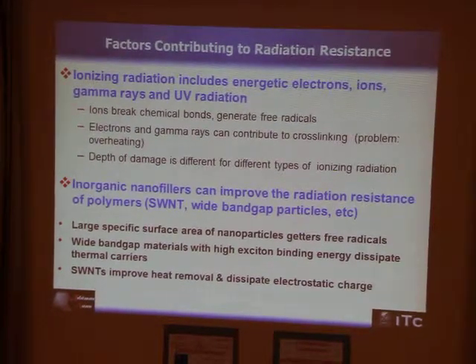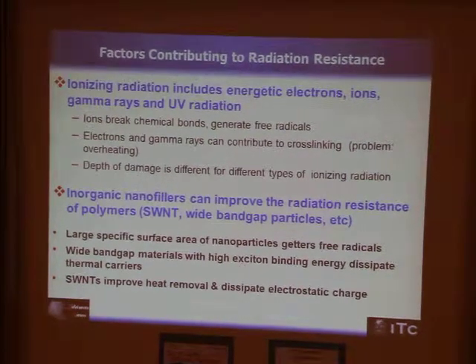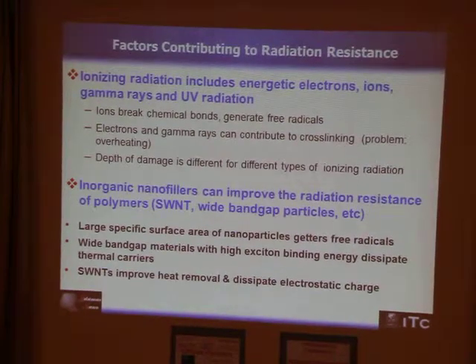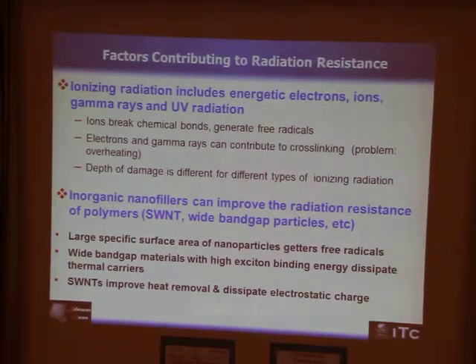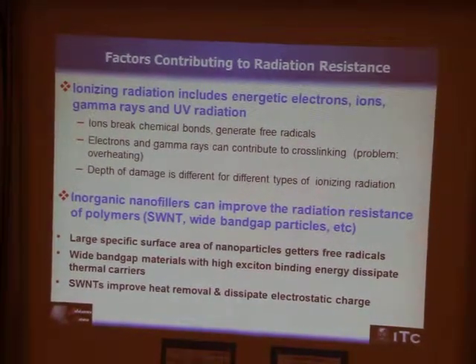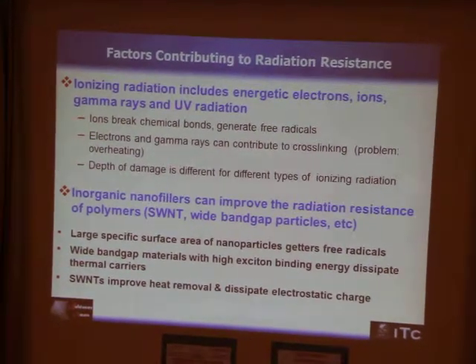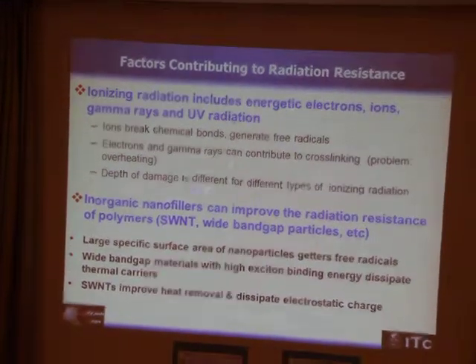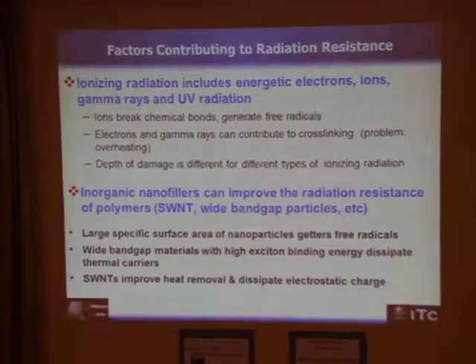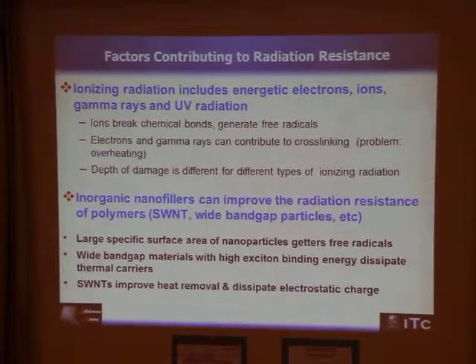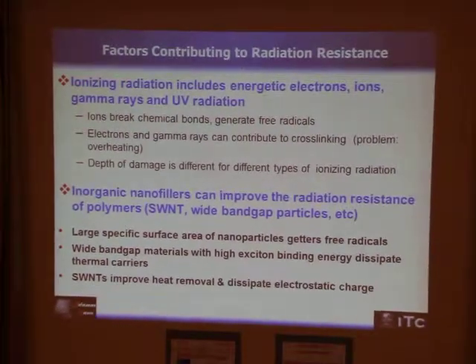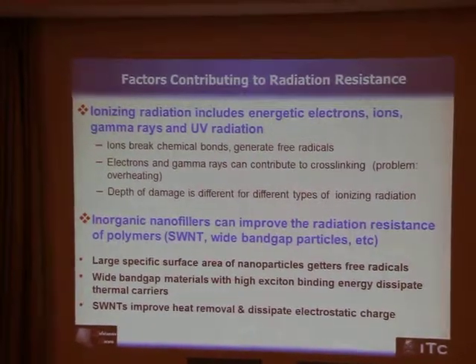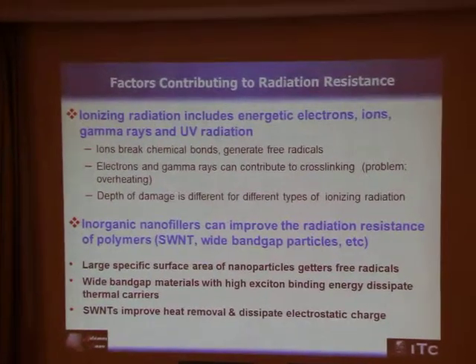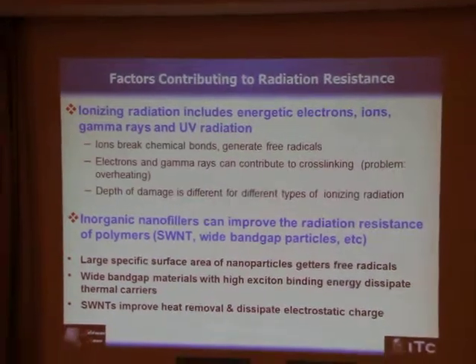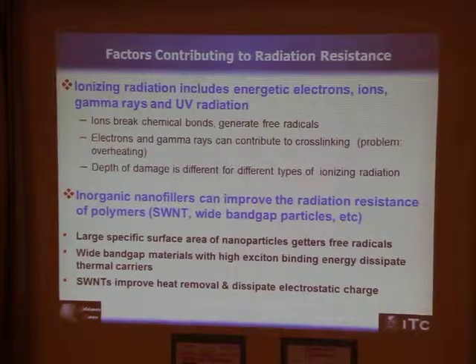It was discovered within the last decade that inorganic nanofillers can improve the radiation resistance of polymers. Single-wall nanotubes were actively used in such studies, as well as wide-band gap particles such as zinc oxide, for example. Mechanisms which are discussed to contribute to these improvements of the radiation resistance are due to the large specific surface area of nanoparticles, which can gather free radicals formed by ionizing radiation. It is also a hypothesis that wide-band gap materials with high exciton binding energy can dissipate thermal carriers and help in thermal budget release of the irradiated polymers, and single-wall nanotubes improve heat removal and dissipate electrostatic charge when they are in a percolation threshold mode.